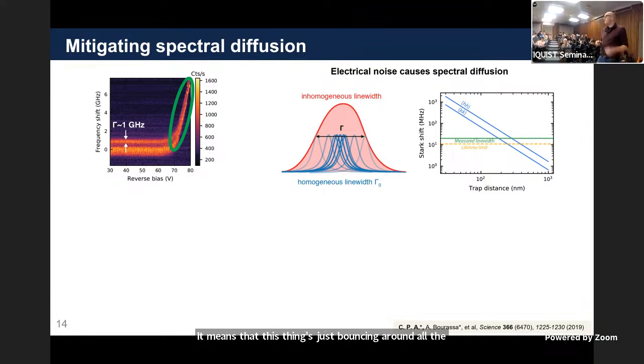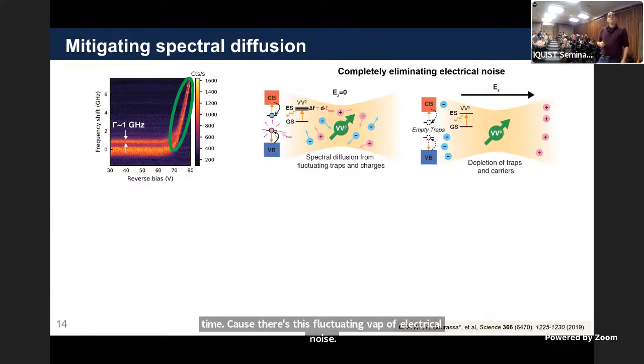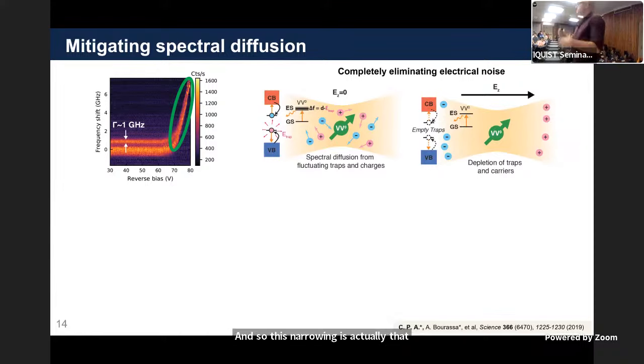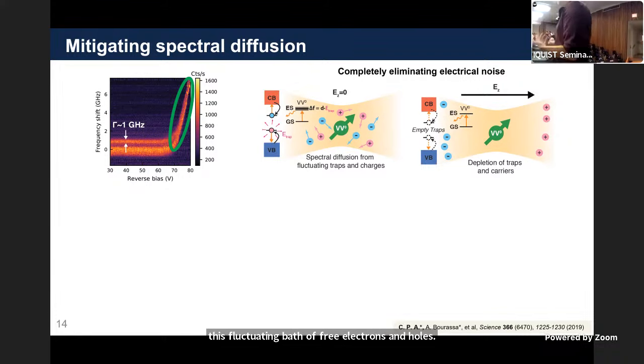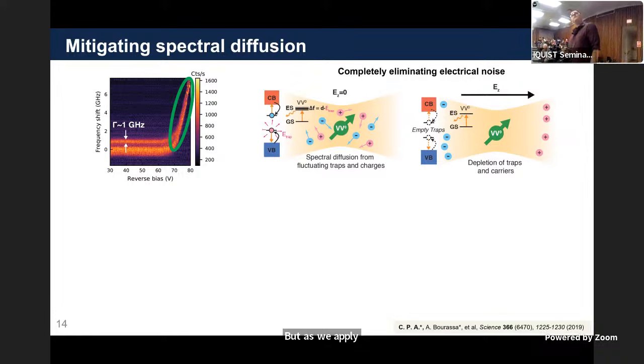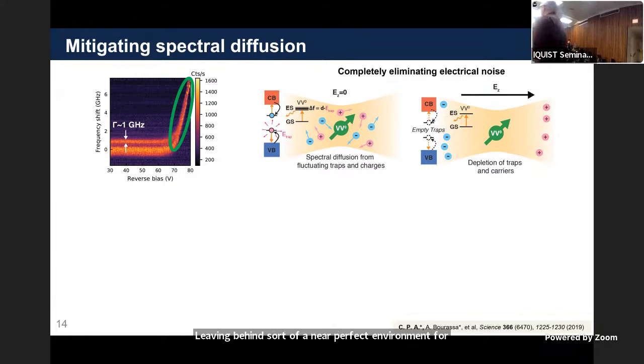And so this narrowing is really, really cool because what it means is that at zero bias, we have this fluctuating bath of free electrons and holes. But as we apply a reverse bias, as we make this depletion region in the semiconductor, we drift and diffuse away all of the free electrons and holes, leaving behind a near perfect environment for our two-level system to live. So because we have this semiconductor control of the system, we can engineer all those fluctuating charges to go away, leaving behind a very coherent two-level system to play with.